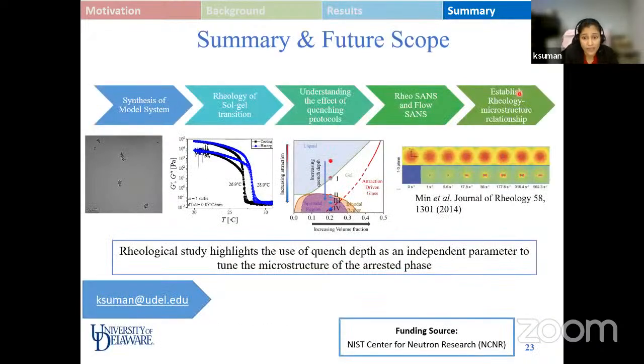So in order to summarize this whole work, we had a system of adhesive hard spheres, which was thermoresponsive in nature. Interestingly, it showed interesting behaviors when subjected to thermal quenches deep enough to enter the two-phase region, where it undergoes a transition from a homogeneous gel to a spatially heterogeneous gel. Now, this is ongoing work, and we plan to do scattering experiments in the linear domain as well as in the non-linear domain to see how we can fine-tune this transition and use it to characterize and obtain different microstructures using quench depth as a parameter.